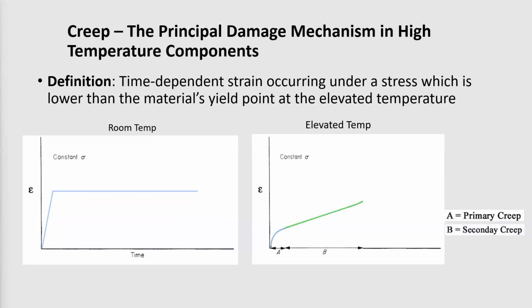And so oftentimes when people are describing creep damage and the strain accumulation associated with it, you'll see schematic curves such as this, which identify a primary, a secondary, and a tertiary phase of the creep damage. This is a highly idealized picture of how creep strain is developed. The important thing here is that as creep damage is accumulated, as reflected in accumulating creep strain, over a period of time the rate of that damage will accelerate as more damage is accumulated, and ultimately will end up in failure.